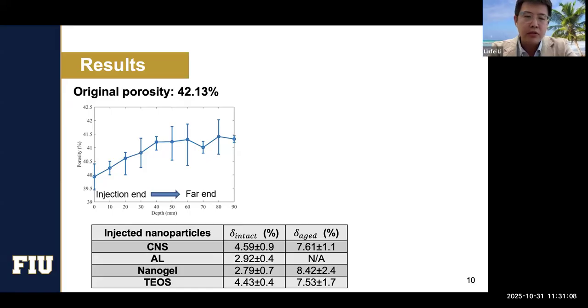We're trying to measure how the nanoparticles seal the cracks, and it's pretty tricky to measure. So we started with porosity measurement. We have the sample, we cut it into slices every 10 millimeters, and then we measure the average porosity of each slice.